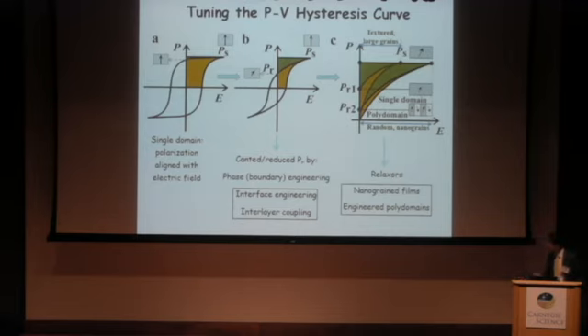So here I'm going to mostly talk about the PV hysteresis. Here is a very classic PV hysteresis. For example, if you have a single domain tetragonal film, your polarization is aligned with the electric field, so there's not too much you can change. Your remnant polarization is about the same, slightly lower than saturated polarization. So this is very good for memory, as we all know.